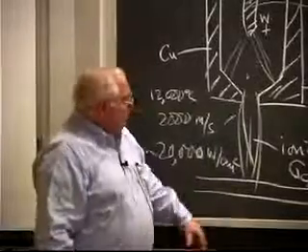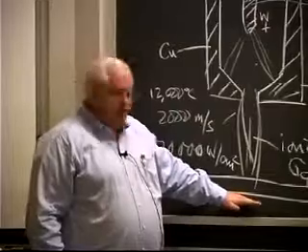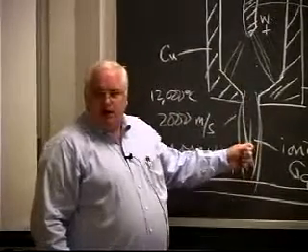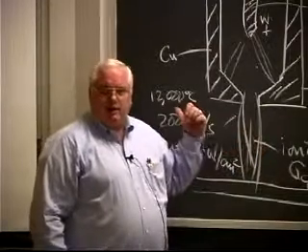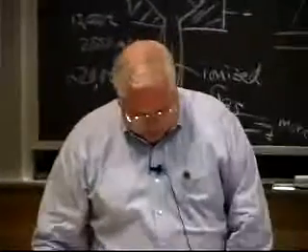So it turns out there's what we call transferred arc plasma processing, where you have to have a conductive substrate because you're carrying 100 amps or 200 amps of current through here. And there's non-transferred arc plasma processing, which has 10 times lower heat intensity, but you don't have to have a conductive workpiece. You can use a piece of ceramic. So if you want, you could use a non-transferred plasma arc to do your hole drilling in rock. Except it'd be a very, very expensive thing that you're putting down the borehole and you tear it up very quickly. But we can talk about some of that stuff a little bit later.